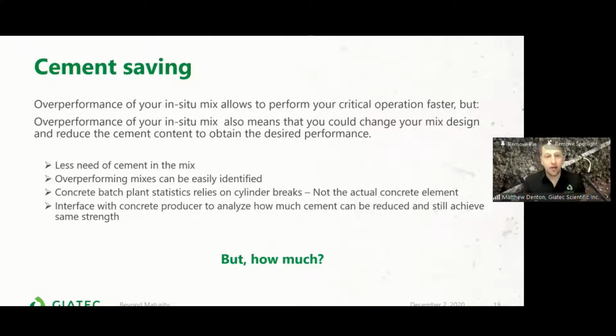Oftentimes, we're over-designing our mixes to be safe. We're over-designing our strength on our concrete mixes to make sure that we cover ourselves, because we're using a method like crushing samples, like crushing cubes, as an indicative sample of what should be happening on site. And we know the liability and the issues around that are always a big factor, and therefore we're always adding that extra safety factor. We're always over-designing our mixes just to be 110% sure that we're hitting our strength. But with the right data, with the right information, with real-time data, we are able to make a difference, have an impact on the amount of cement that we need for our standard concrete mixes.